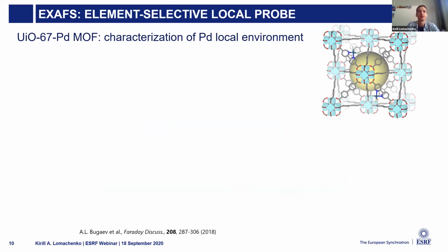UIO-67 MOF functionalized with palladium. It's a cubic MOF with the majority of linkers that are biphenyls, but some of them are substituted with bipyridine, with palladium grafted to it, coordinated also with 2 chlorine ions.